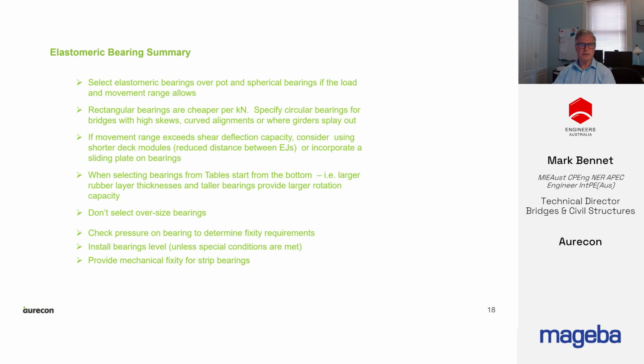So just summarising for elastomeric bearings, select elastomeric bearings over pot and spherical bearings if the load and movement range allows. Rectangular bearings are cheaper per kilonewton. Specify circular bearings for bridges with high skews, curved alignments, or where girders splay out. If movement range exceeds shear deflection capacity, consider using shorter deck modules, reduce distances between expansion joints, or incorporate a sliding plate on bearings. When selecting bearings from a table, start from the bottom. Larger rubber thickness and taller bearings provide larger rotation capacity. Don't select oversized bearings. Check pressure on bearing to determine fixity requirements. Install bearings level unless special conditions are met, and provide mechanical fixity to strip bearings.